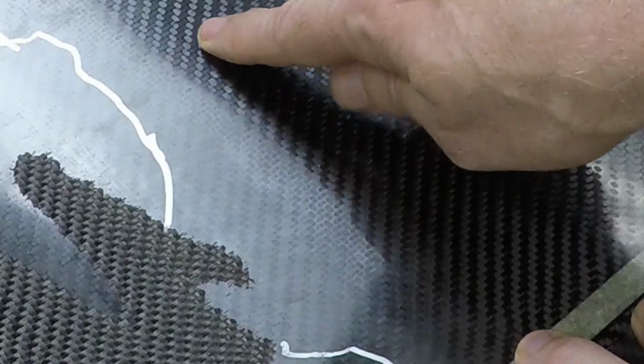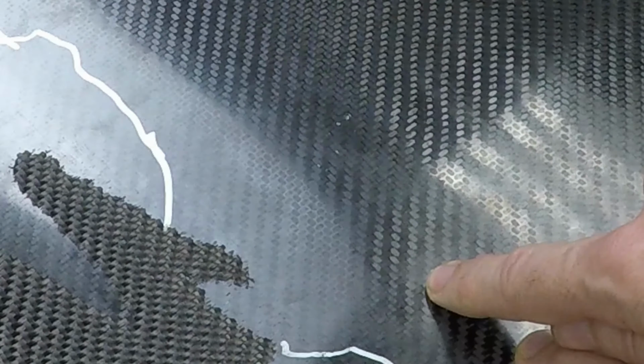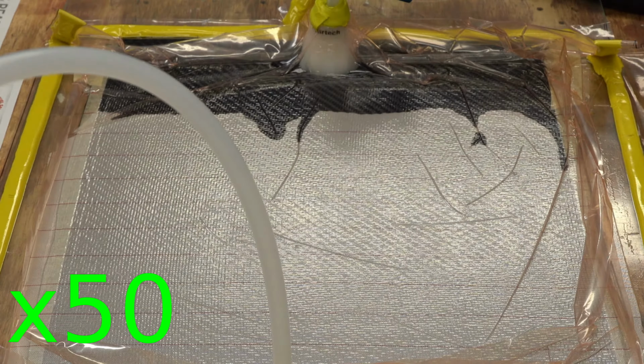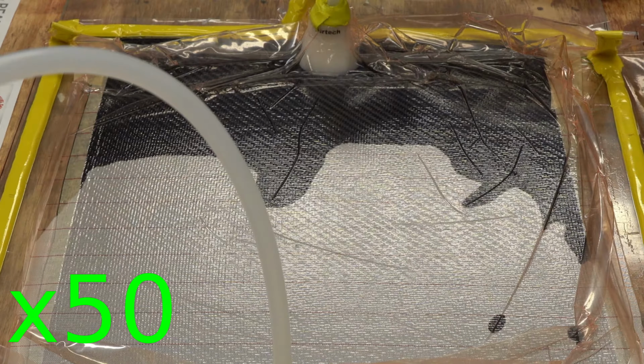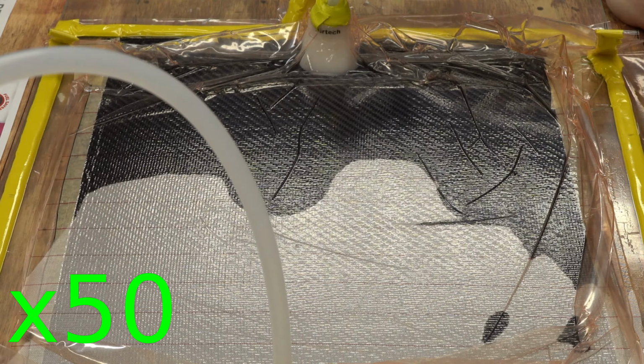So I thought, well, you know what? This finish is fantastic. The area where I was able to get the resin to flow through, I had a great finish. I was very excited about that. So that was the first time I'd had a good finish on a sample. So I said, hey, we're in the ballpark. If we can just get that epoxy to flow through a little bit better, we'll get a good sample. While I was performing the vacuum infusion on this last test, and on many other previous tests, I had noticed that the epoxy likes to flow through wrinkles in the peel ply faster than when there are no wrinkles. And I thought, well, what if I intentionally put wrinkles in the peel ply running down the length in the direction that I want the resin to flow? Maybe that will help the resin get to the far end, to the vacuum end, before it starts to gel.